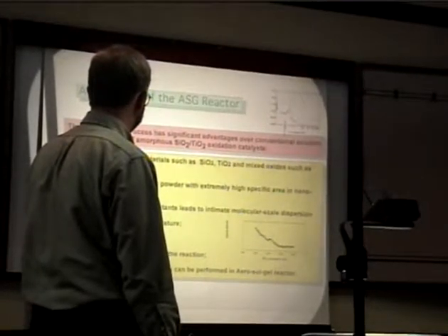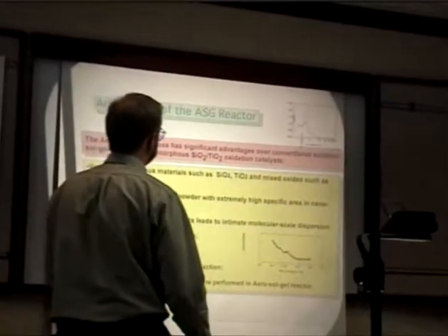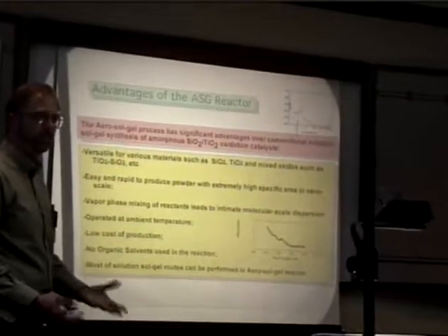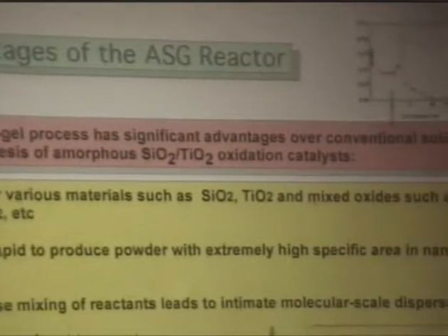Okay, so we're looking at this as a highly versatile and clean reaction where we're reducing the consumption of, say, solvents that you need in a solution route. The versatility comes from the idea that in an aerosol you can force miscibility without solvents. Vapors mix, and if you condense a vapor, you can co-condense things that don't normally co-condense. And also because there are such small droplets, the transport rate of reactants into the droplets and byproducts out can enhance the reaction rate by a factor of about 10.